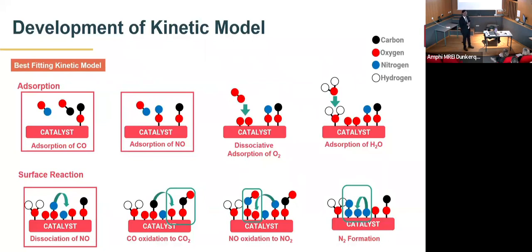For example, if you want to see NO2, you have to first determine which reactions lead to NO2 production. In our case, the NO2 production is led by the NO oxidation reaction, so NO reacts with oxygen to form NO2. So we first try to find out which step of this reaction can be rate limiting. And then we say, okay, the rate of production of NO2 can be determined by the rate limiting step that we have. In this case, adsorption of NO. Okay. So if your objective is to perform the reduction of NO to N2, the limiting step is the dissociation of NO.